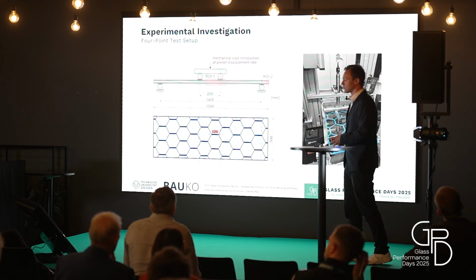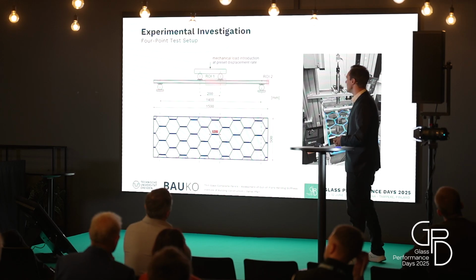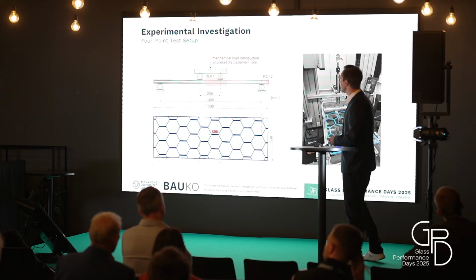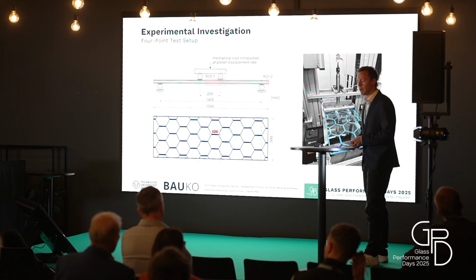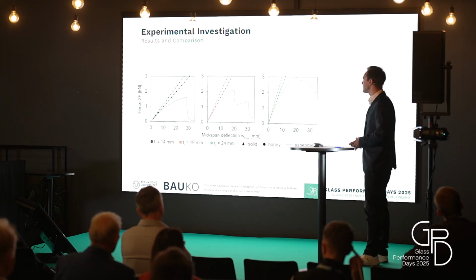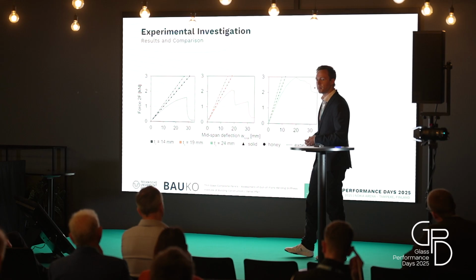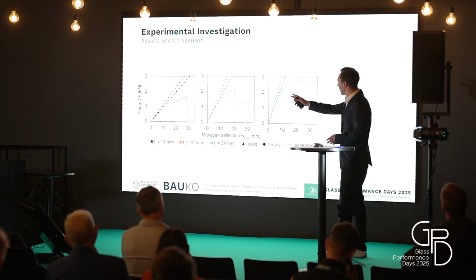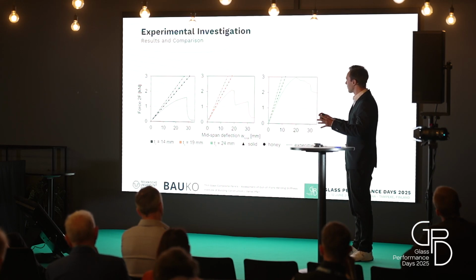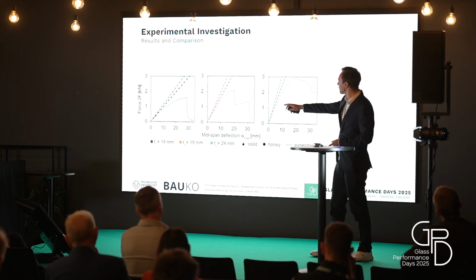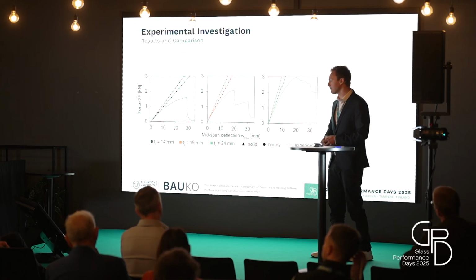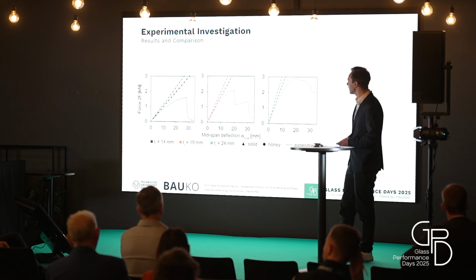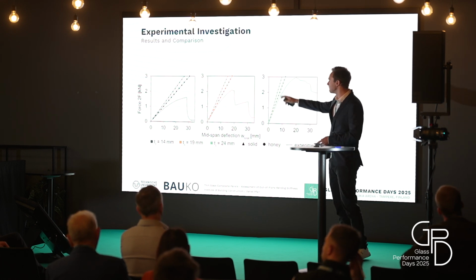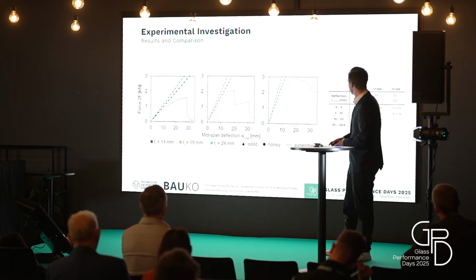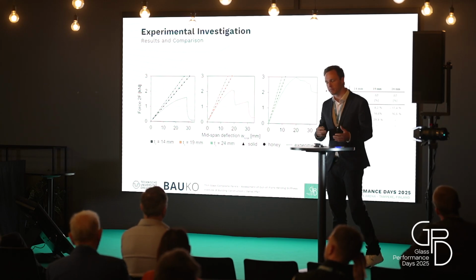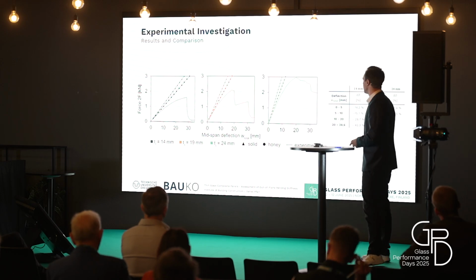Which brings us right now to the experimental investigation. We have our 4-point bending setup on the left-hand side, and on the right-hand side a picture from our laboratory where we have tested, and this gives us our results and already the comparison to our analytical model. We have the 3 diagrams representing the 3 different thicknesses, and in each one we have the triangle, which is the solid assumption, the circle, the honeycomb assumption, and then our experimental line for each of the 3 thicknesses.